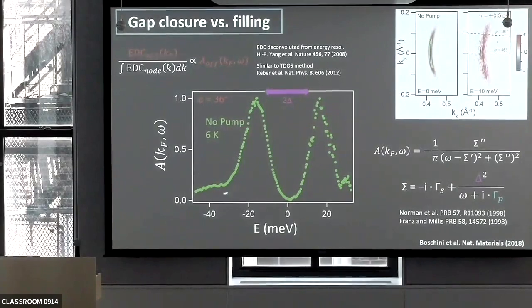The surprising part is that not only do you see a peak below EF, but you also see a peak above EF. And this is where the sensitivity of the experiment and the ability of the experimentalists comes in. You are basically seeing data which are measured well above the chemical potential, and you still can see the occupation of that state at this very low temperature. And this requires very high statistics. Of course, Andy is surprised by this, but this really requires very high sensitivity, very high statistics, and then you have to divide off a Fermi function.